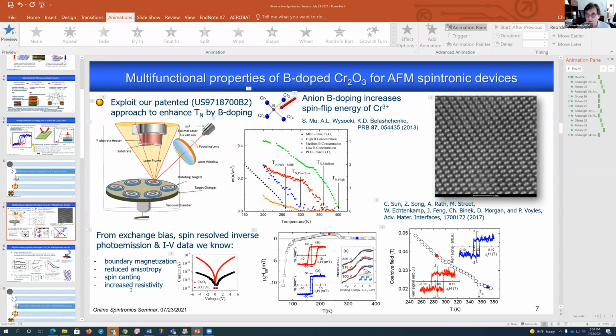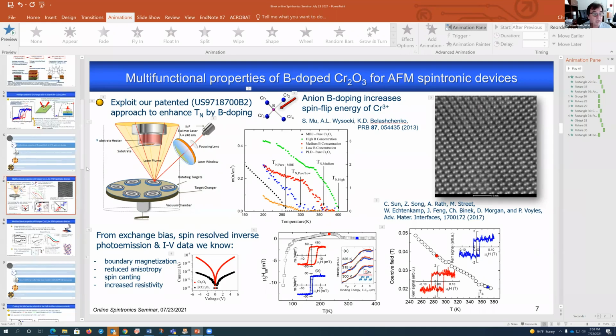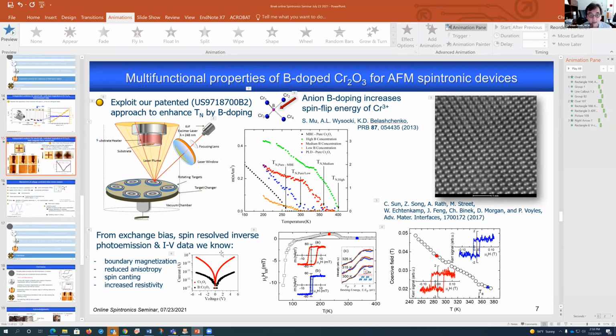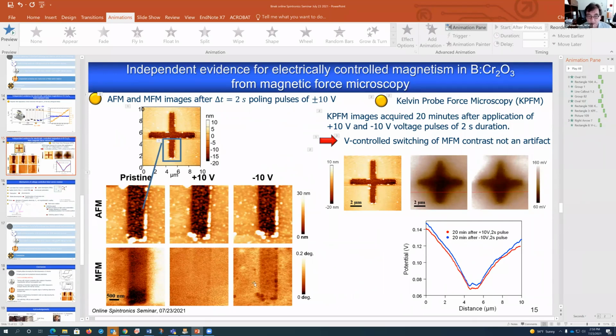Now, in our case, this is exactly the reason why we teamed up with Grundler, and we wanted to make sure that we have a method that is not dependent on this transport data that can show that the effect is indeed magnetic. But we are not stopping there. We go on, and we just today formulated a beam time proposal. And of course, we want to see directly the rotation of the order parameter by XMLD. And similarly, I want to see the rotation of the order parameter by XMCD.